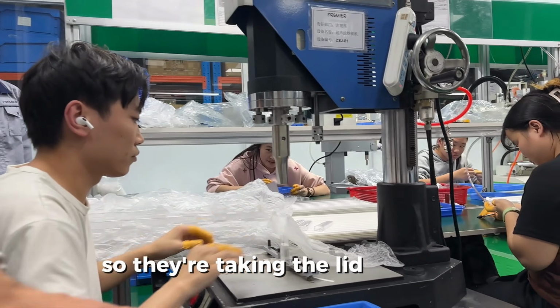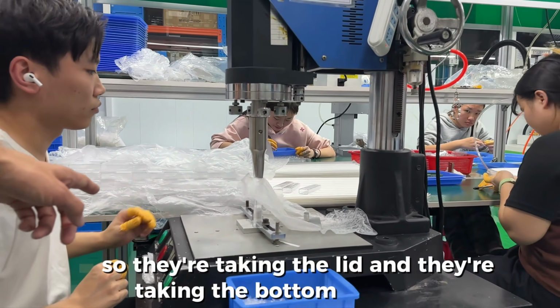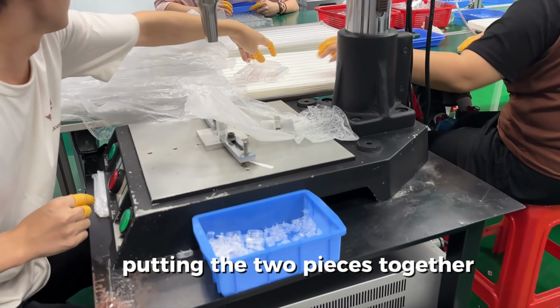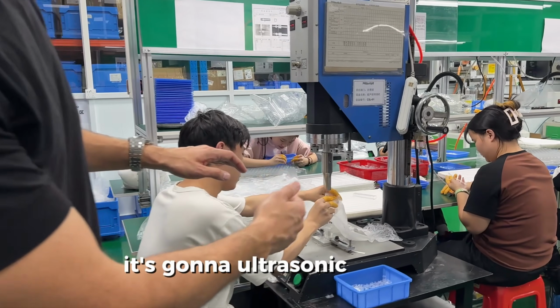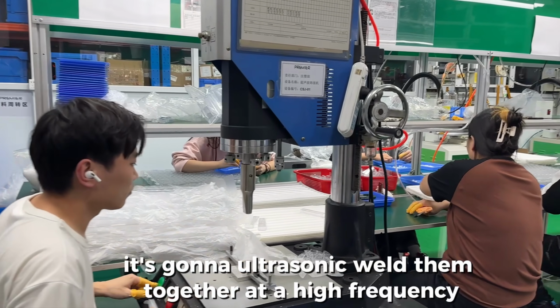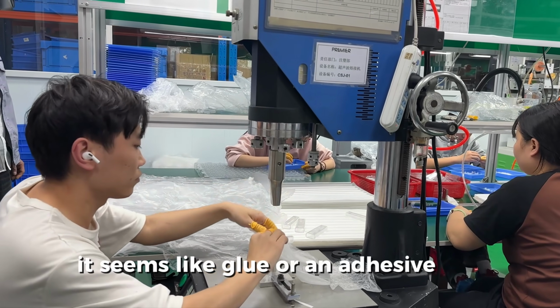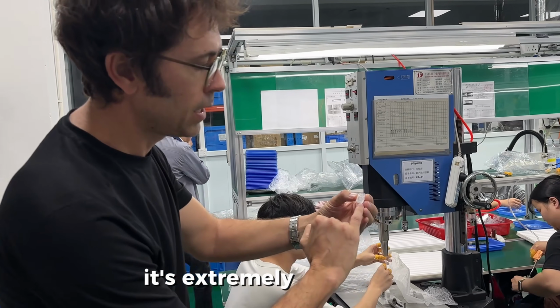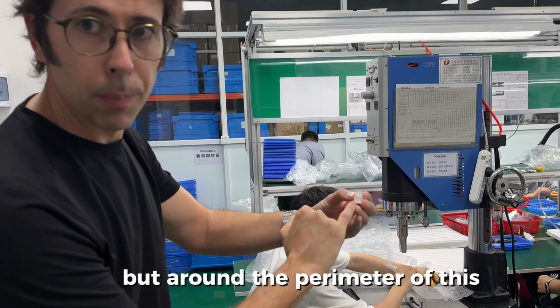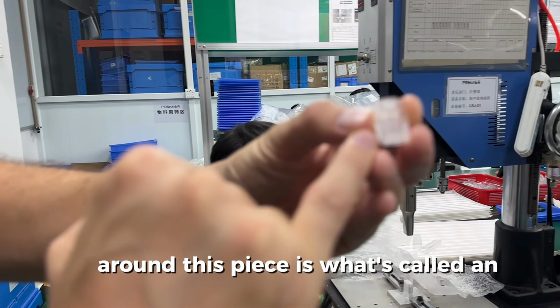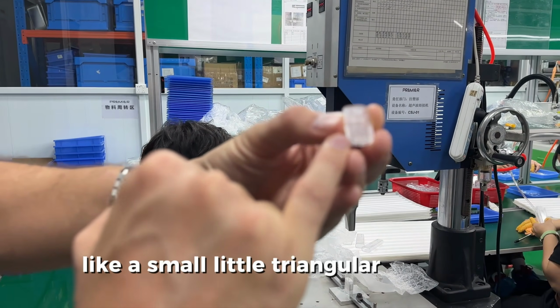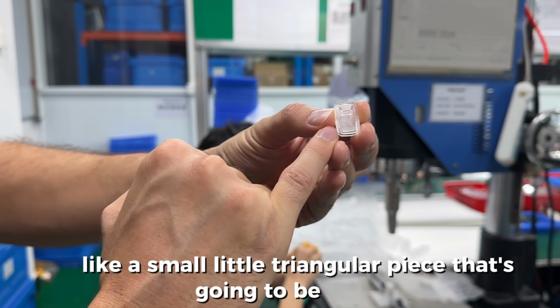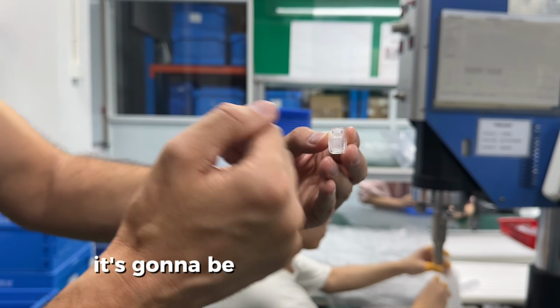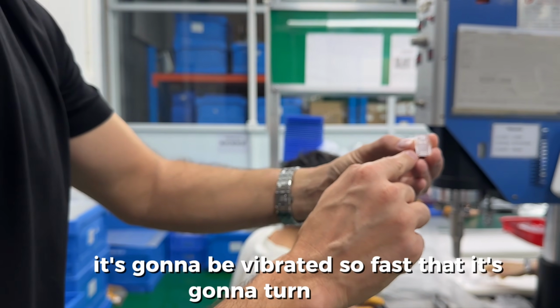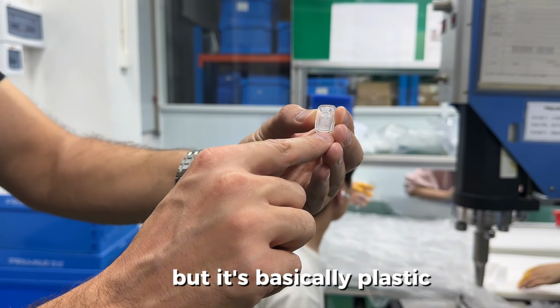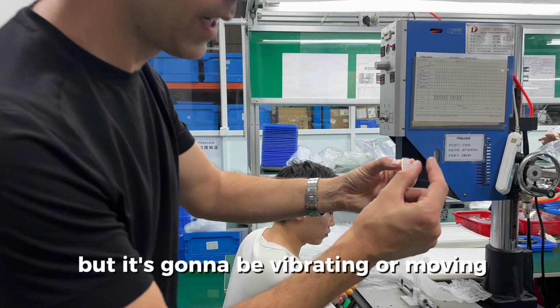They're taking the lid and the bottom and putting the two pieces together manually. It's going to ultrasonic weld them together at a high frequency. It seems like glue or an adhesive, but it's not. It's extremely difficult to see, but around the perimeter of this component is what's called an energy director, a small little triangular piece that's going to create friction. It's going to be vibrated so fast that it turns into basically melted plastic, because it's moving so quickly.